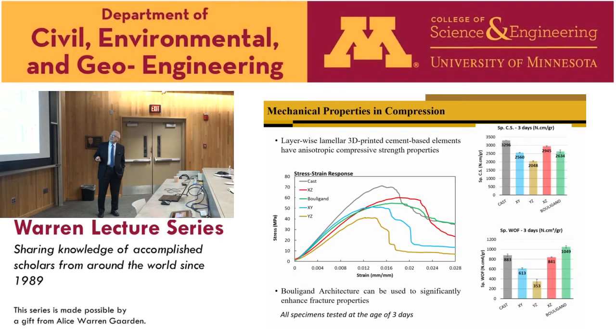So this is a stress-strain response, and again, you can see that in some cases, like this red one, when it's loaded in the XZ plane, it has almost the same value of stress. It has actually a greater ductility than the cast material. But if I load the same material in the other direction, it's not going to behave as well. So from an engineering point of view, you would have to decide how you are going to use the material that you print. And if you want to take advantage of this increased ductility, you need to orient the element accordingly in your structure.